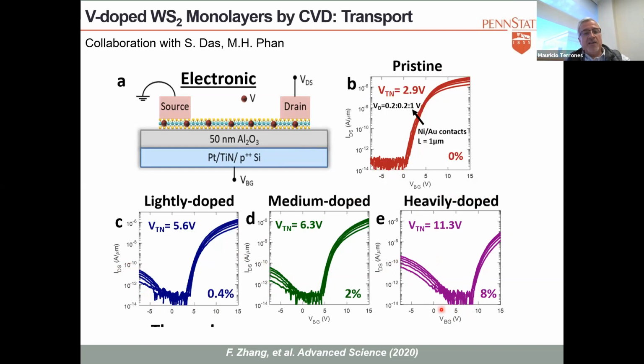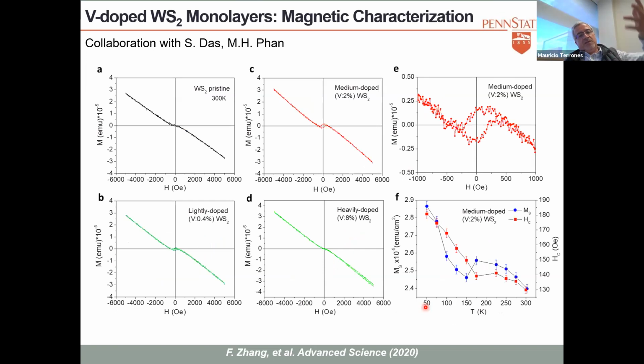So again, this is nice. So we start changing the transport properties. We see that the structural properties also change. But to our surprise, we could still start seeing some ferromagnetism here. So this is the ferromagnetism. It was interesting because we saw the most intense ferromagnetism when we had medium dopant, right?